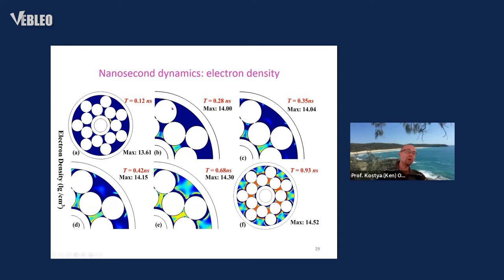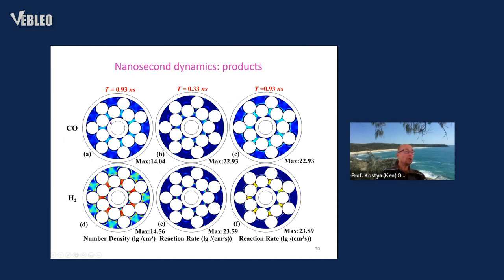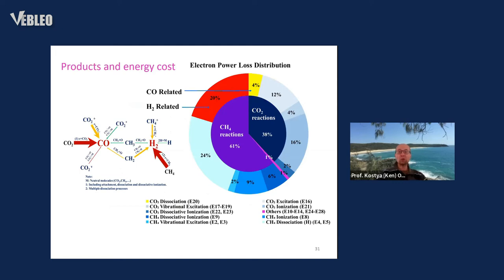If you see the temporal dynamics of those processes, that lasts over nanoseconds and continues between the pulses also. The more we look into the interspaces between those catalytic beads, we see more CO and hydrogen are generated with time. So the number density of the products can be controlled by the plasma parameters, by the catalyst parameters, and as a result, one can tune what we produce as a result of these catalytic reactions.